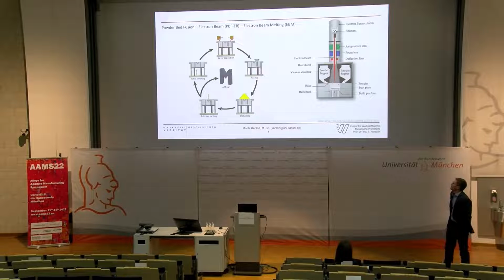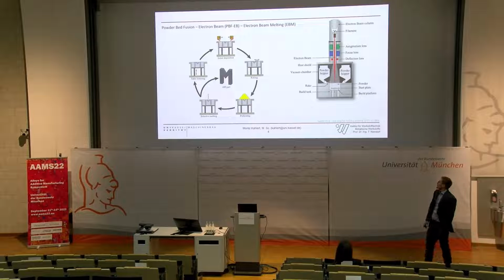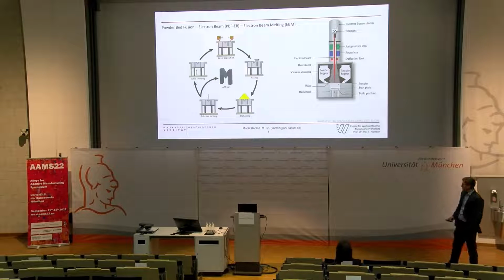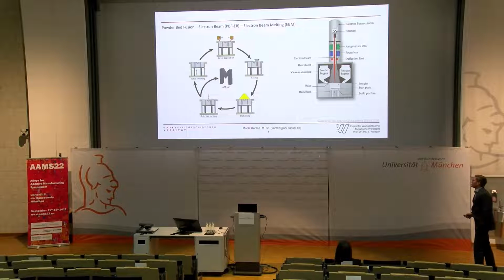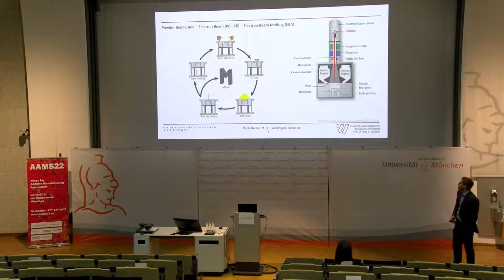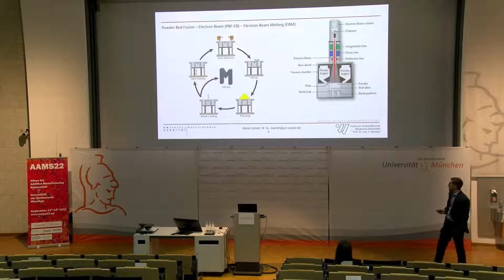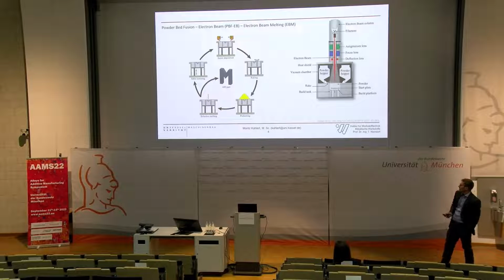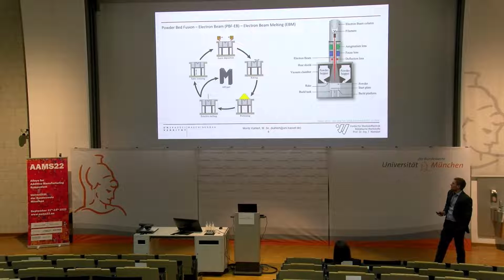Powder bed fusion with the electron beam is called electron beam melting. It is a typical powder bed fusion process. It starts with a layering of powder, then raking, and then there is a step which makes it different to the SLM process: the preheating. This step is necessary to increase the conductivity of the powder, preventing powder blast in the process. The whole process runs at high temperatures, and the electron beam is the source of the melting. After this, the table is lowered and the process is repeated until the part is finished.